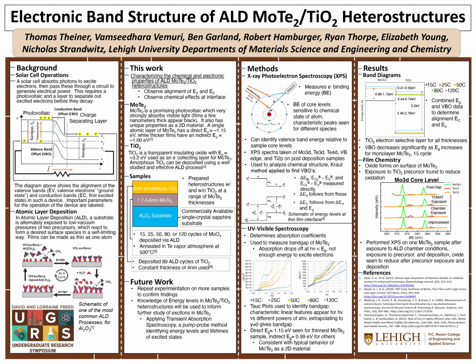And the same thing happens when you put in the other precursor, which is just water. And that reacts to form some alumina, and then you repeat this over and over again and slowly grow up that alumina layer. We didn't grow alumina in this study, but we did grow molybdenum oxide and titanium oxide.